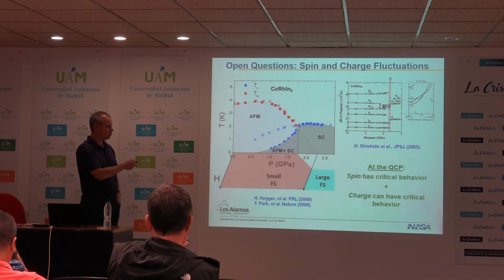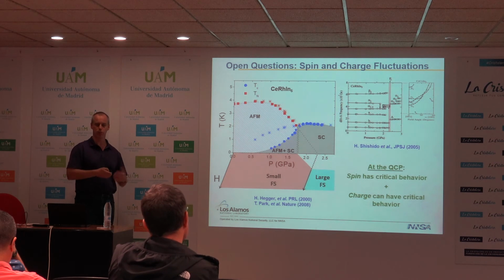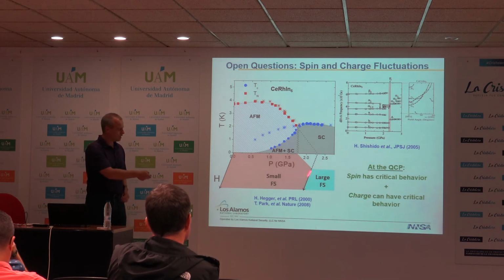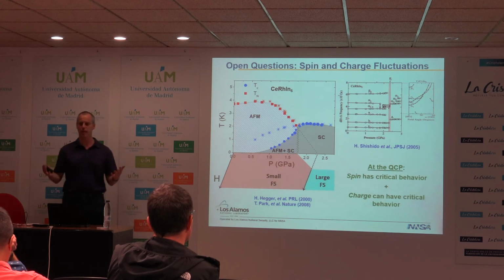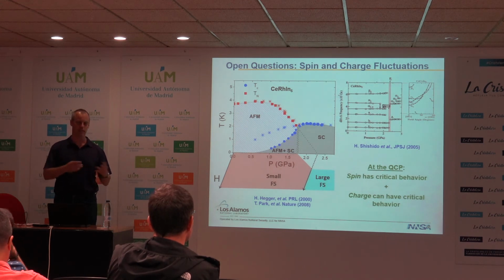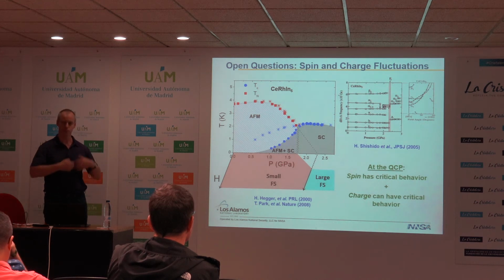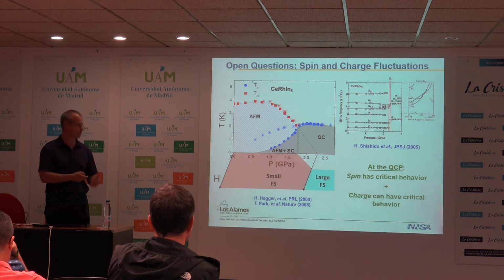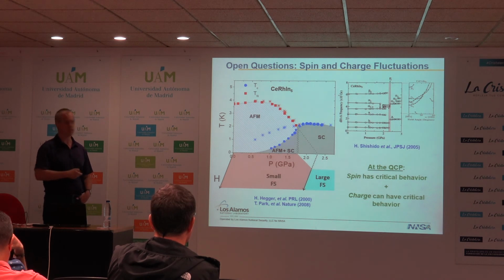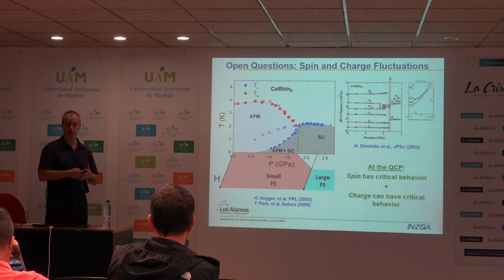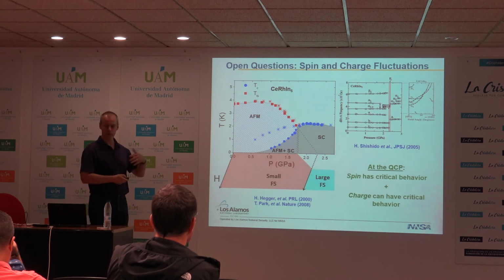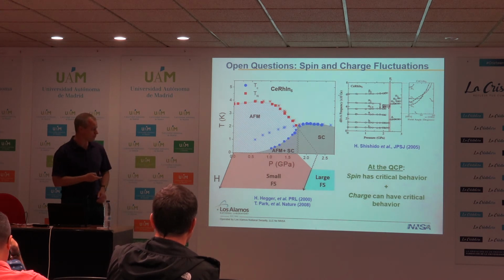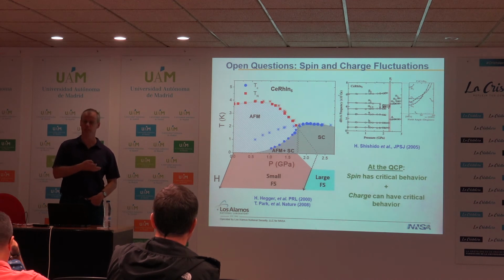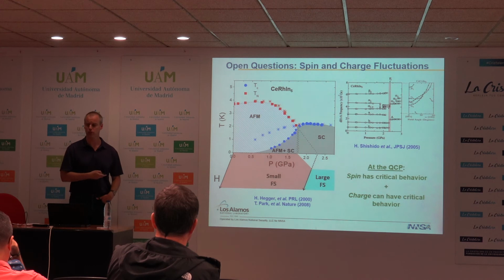Okay? So this actually shows that not only do we have spin fluctuations, but we have a reconstruction of the Fermi surface precisely at the point where you go from small to large. And this is not just the magnetic zone folding that you would expect from antiferromagnetism. You actually get this incorporation of the f-electron degrees of freedom into the Fermi surface. So we have both spin fluctuations and presumably some form of charge fluctuations at this quantum critical point, which is also perhaps making the understanding of the normal state even more complicated, but something that may also play a role for the superconductivity. In fact, it's an interesting question of whether the spin fluctuations or the charge fluctuations are perhaps promoting superconductivity more.